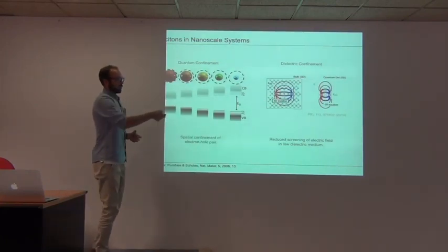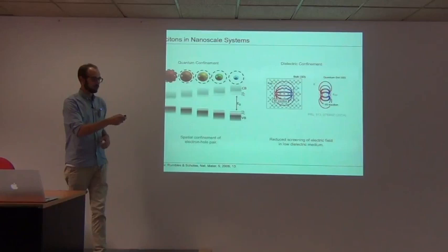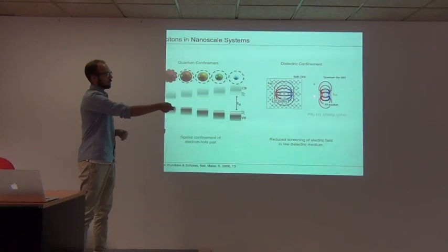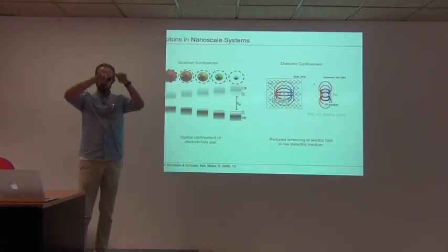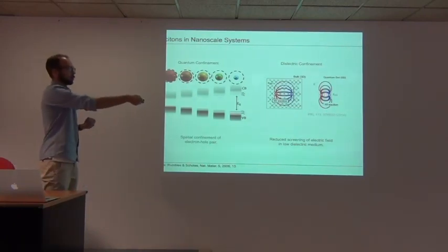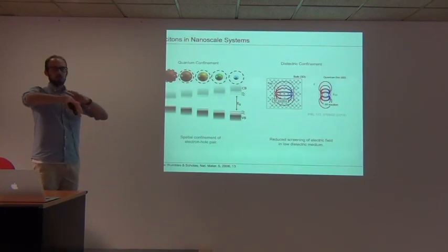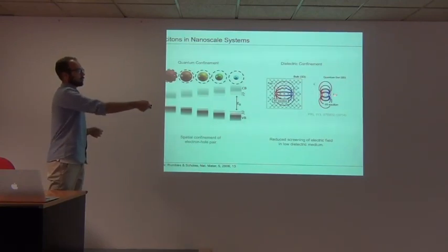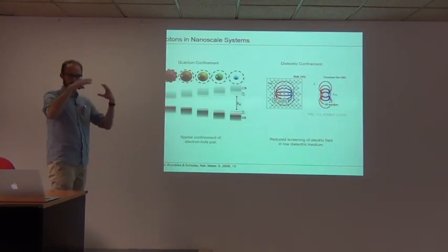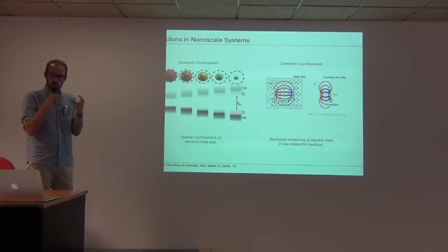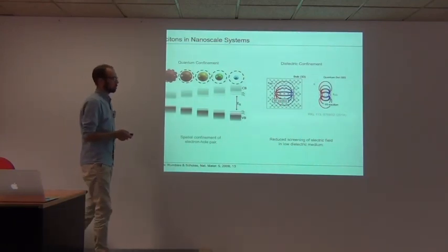If we draw these field lines in a large bulk material, then these field lines will see the same dielectric constant all throughout. Whereas in a tiny particle, these electric field lines are now extending beyond the size of the particle. So when we are describing these kinds of excitons, we need to take into account the effective refractive index or the effective dielectric constant of the environment, both taking into account the tiny semiconductor nanoparticle, but also perhaps the more organic environment. So these two effects together lead to this very sensitive tunability of the system.